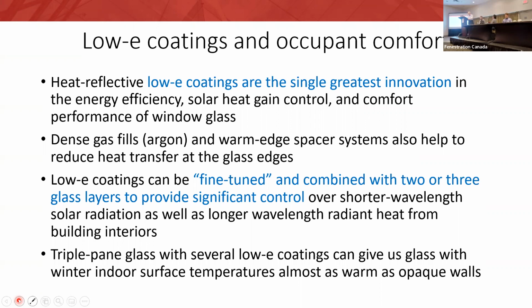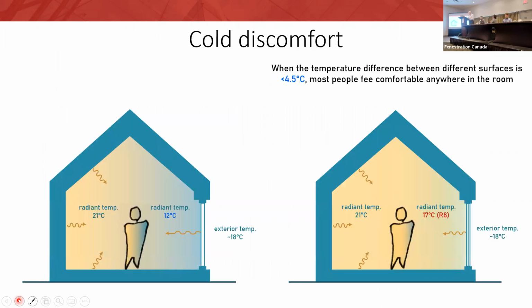We know that with triple pane glass having at least 2 low-E coatings, we have glass that will have winter indoor surface temperatures that are just a couple degrees cooler than our walls. And when you get that balance right, you feel comfortable outside the window or away from the window. These are diagrams that you often see when people talk about Passive House, but they're very useful in trying to explain this concept. What research has found is that when the temperature difference between different wall surfaces in a room is within about 4.5 degrees Celsius, most people will feel comfortable anywhere in that room. Some people will still be uncomfortable near the colder surface, but by and large, most people will feel comfortable.